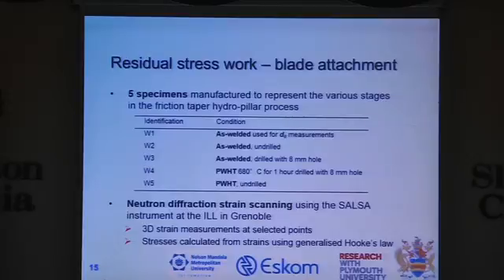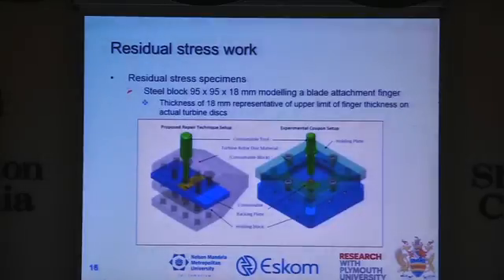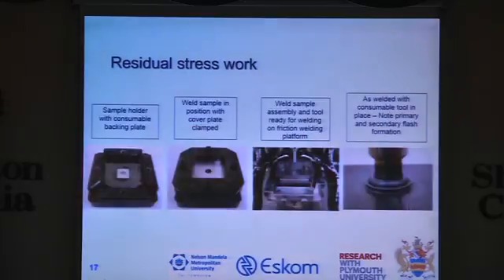You go to SALSA, the instrument at the ILL in Grenoble, and you make your measurements. The reason I put this slide in is that you have to take great care in making sure that the samples you take to the ILL are representative of what's going to happen in real life. If you miss this point, you're going to sit with data that is misaligned with what's happening in the field, and you've not solved the problem with respect to your repair.